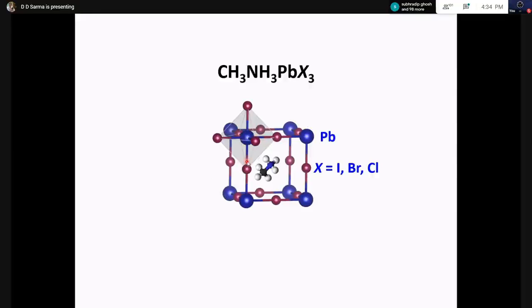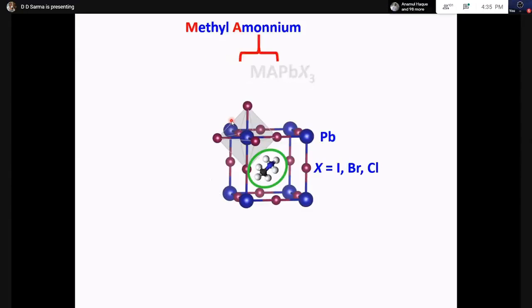that is around there. Similarly, this is connected to the octahedra on that side, and this is connected to the octahedra on that side. So it's basically a 3-dimensionally running chain of octahedra in all 3 directions that makes the 3-dimensional network. And it is stabilized by putting in this void body-centered position this methylammonium, a particular organic molecule. In fact, the original perovskite structure has an inorganic material here, and you can put inorganic and a few organic materials here. And this is the methylammonium, and we'll often abbreviate it as MA, such that it will stand for MAPbX3.